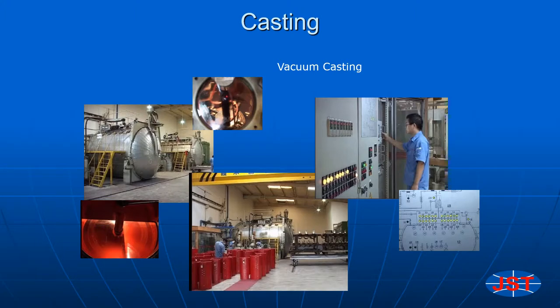Vacuum casting chambers are loaded with molds that contain the wound coil from the previous process. Air is evacuated from the chambers by an oil diffusion pump. While under vacuum conditions, the epoxy resin and hardener are injected into the mold. A static mixing technique is used by JST. This technique is basically opposite of batch mixing and is more of a metered mixing where both resin and hardener are mixed at the time of injection into the mold.